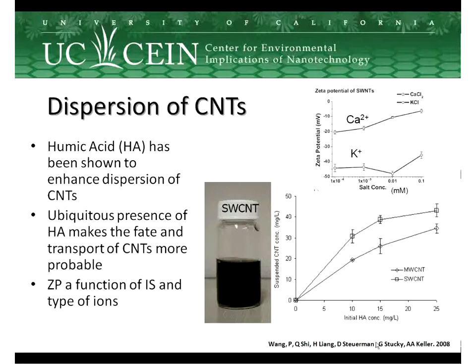And then the charge and how well dispersed depends on the type of ion that's present there. So calcium and divalent ions tend to lead to a less negative charge because they are basically surrounded by a lot of positive charges, whereas sodium and potassium tend to lead to more negative dispersed carbon nanotubes. So these are less likely to aggregate here.